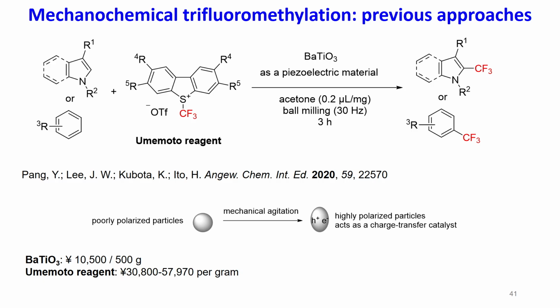And when we just started working, we noticed there was one very interesting report on a mechanical approach to trifluoromethylation. This was reported by the group of Hajime Ito and Koji Kubota. And what they proposed is that they use Umemoto reagent to trifluoromethylate arenes or heteroarenes, and they use this very special additive, barium titanate, that they put in a reaction mixture. So the proposal was that this mechanical agitation in a ball mill deforms this particle. And when you create a polarized particle, this may act as a charge transfer catalyst and cause the single electron transfer events, accordingly initiating the whole reaction.